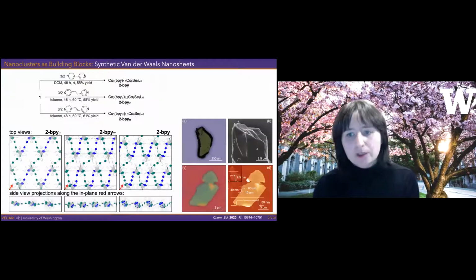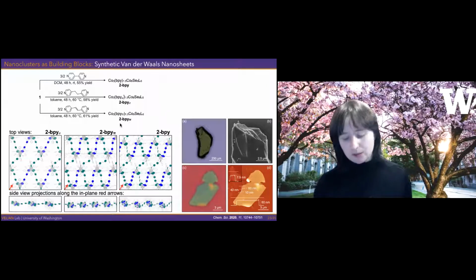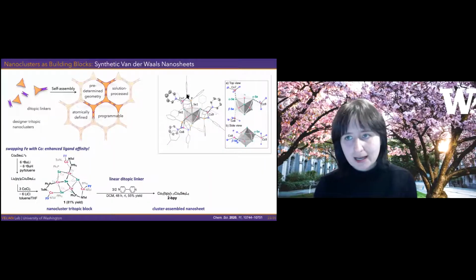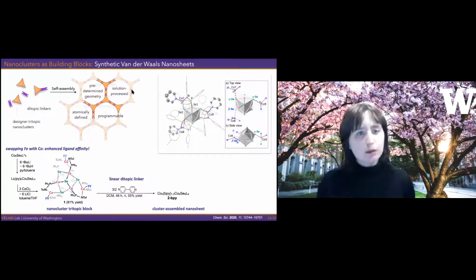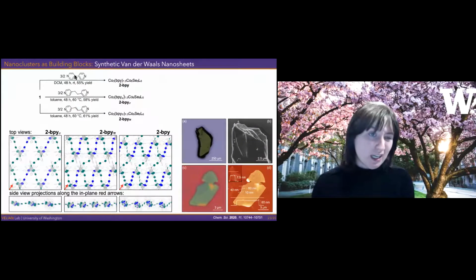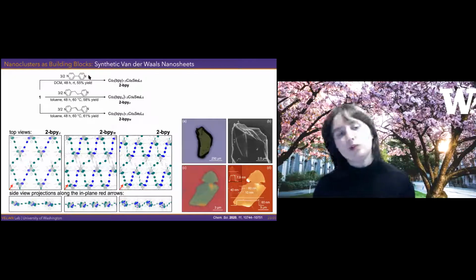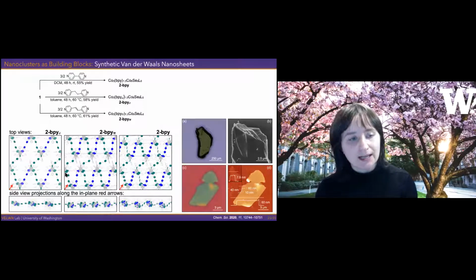In particular, we were targeting 2-dimensional nanosheets. So here we have 3 attachment sites, 1, 2, and 3, and we thought, okay, it's kind of like a triangle. We should be able to get a nanosheet out of it, and that's exactly what we did. We took this linker that is linear and ditopic, with 2 points of contact, and at the end, we form a family of materials. This is just a snapshot into the single layer. They are all layered materials. They're all van der Waals materials, and they're 2-dimensional.